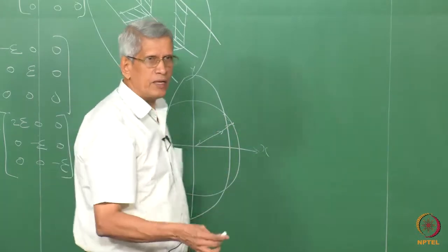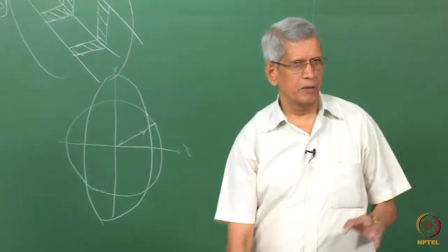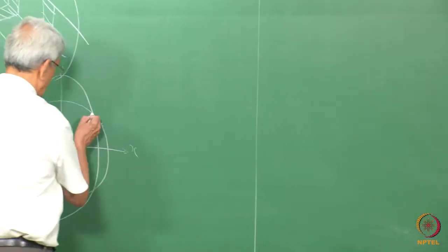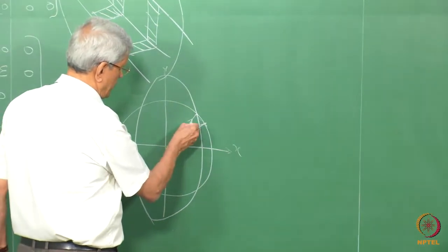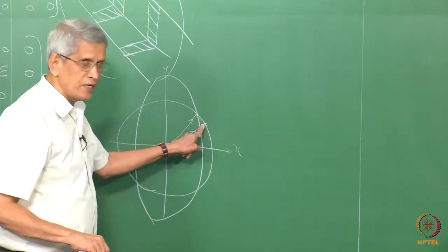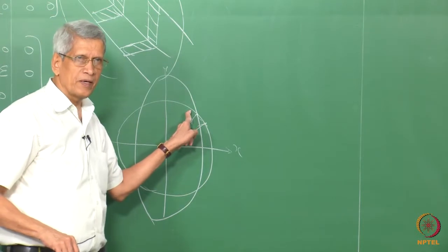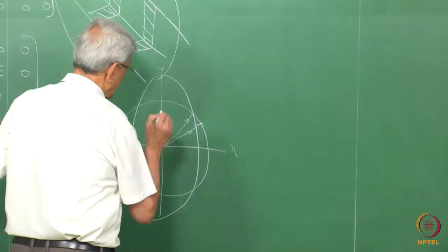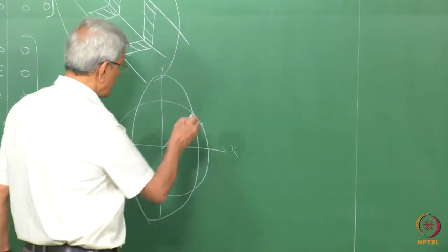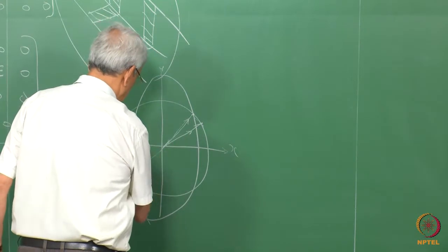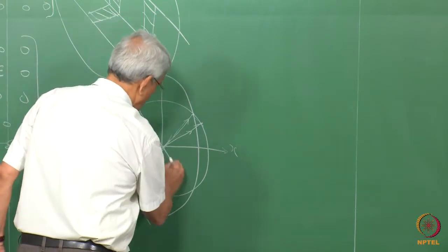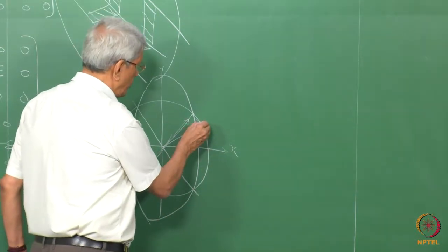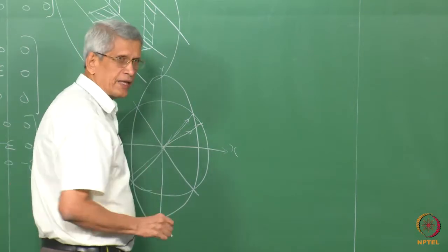After that sphere has been elongated by applying tension in one direction and compression in another direction, this vector has reached this point. So, what has essentially happened is that this vector is rotated but not distorted, correct. And since in the third direction the strain is 0, this will be lying on a plane, correct. So, we have two planes, okay.